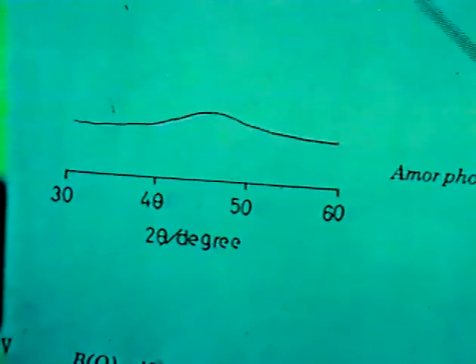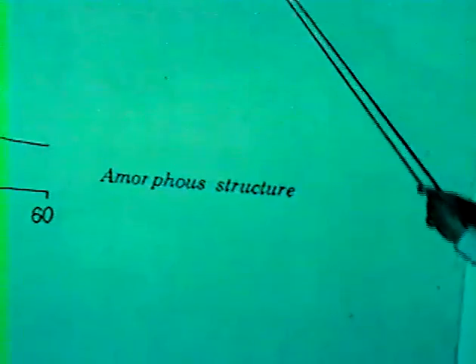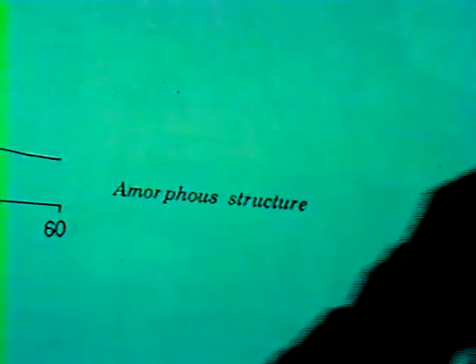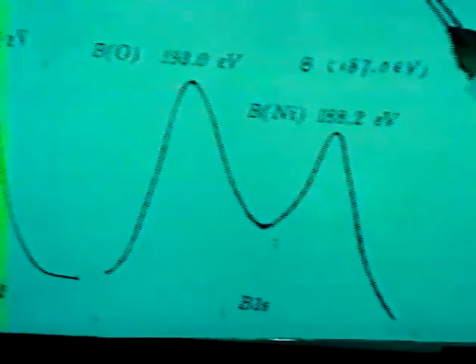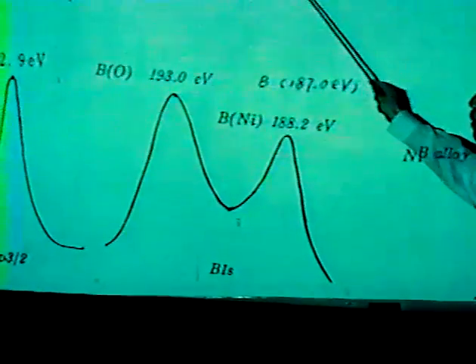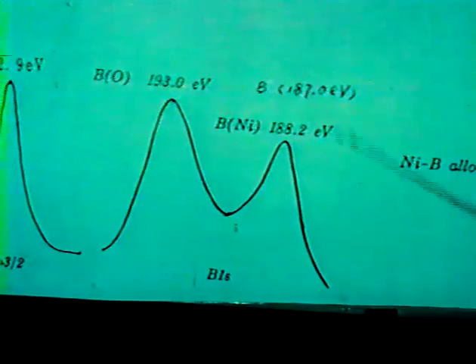This is the transmission electron micrograph of the fresh catalyst. We can see from this figure the particle size ranges from 15 to 50 nanometers. This indicates the fresh catalyst is ultrafine particles. This is the X-ray diffraction pattern. You can see only a broad band instead of discrete peaks in this diffraction pattern. This indicates the structure of the catalyst is in an amorphous state.